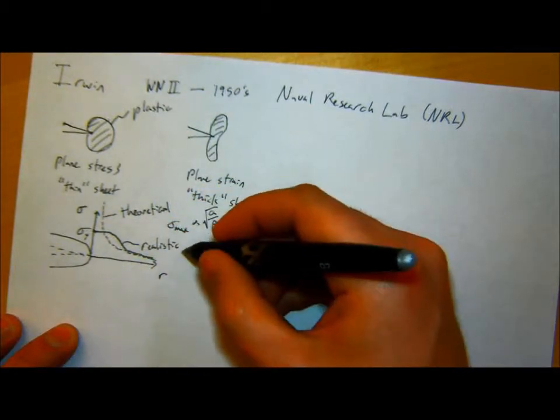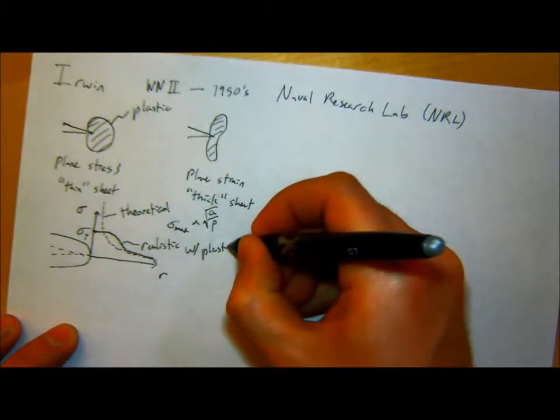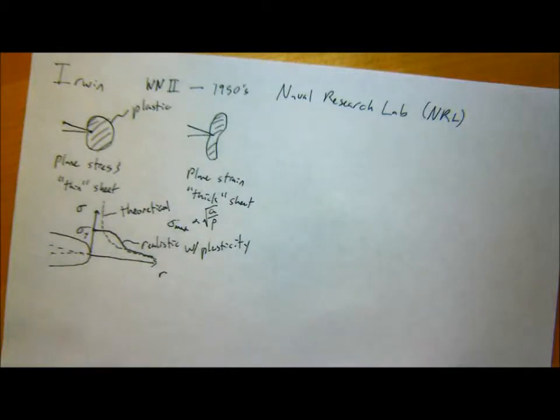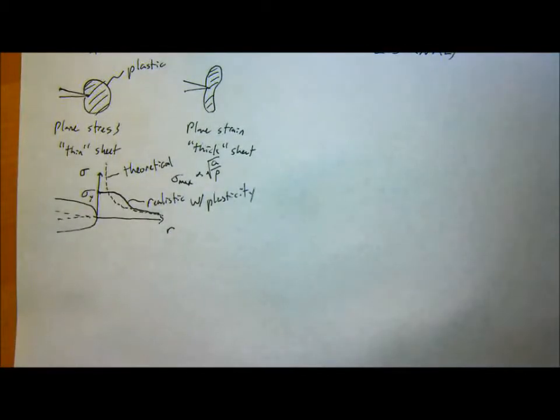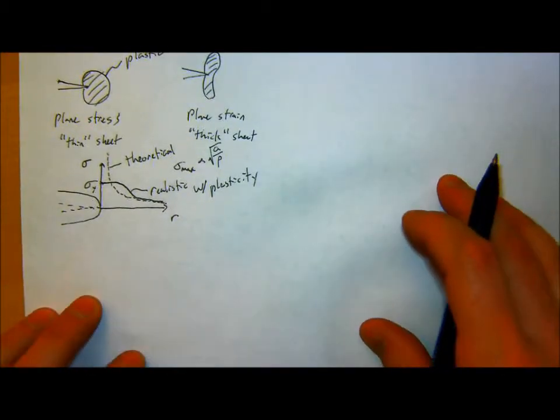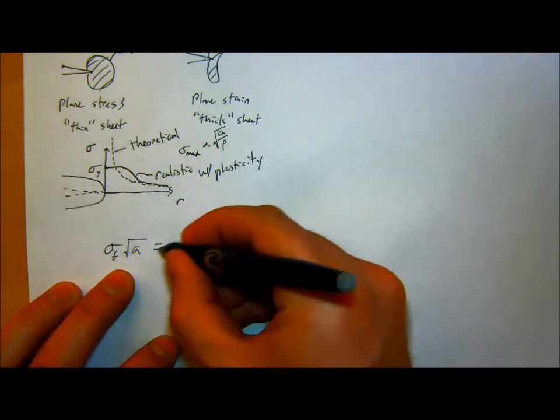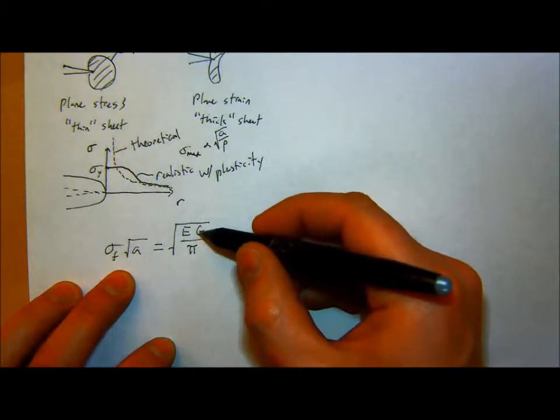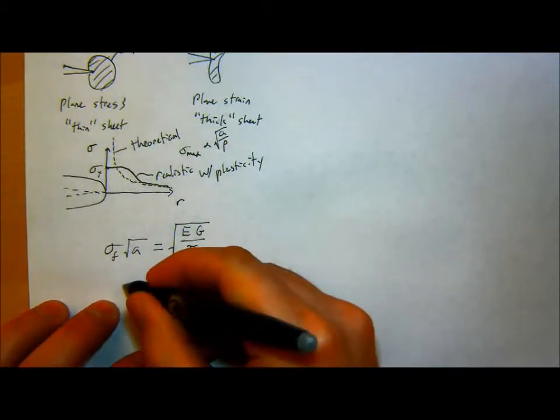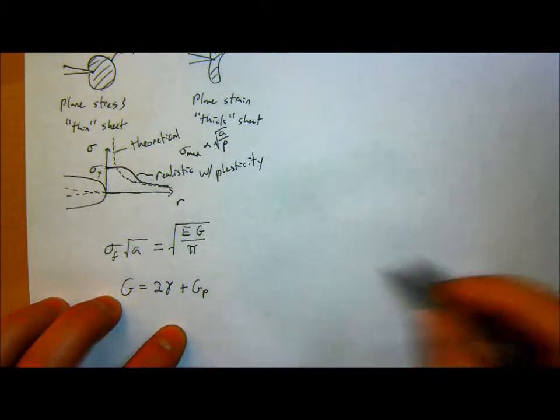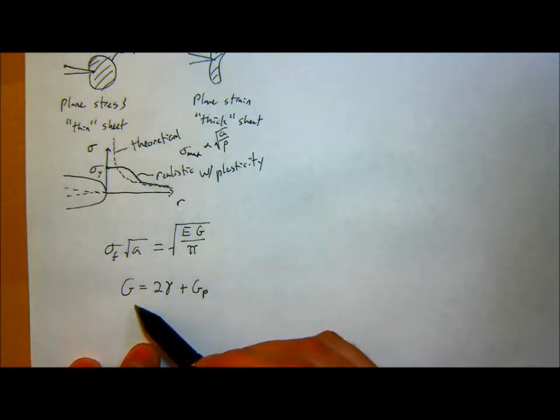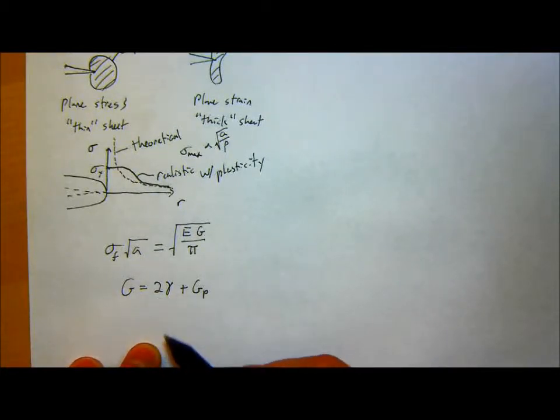So Irwin then proposed a slightly modified version of that fracture toughness relationship. So now we have sigma f square root of a instead is equal to the square root of EG over pi, where before I had a 2 gamma for the surface energy. This G now is going to be that surface energy term plus plastic dissipation energy. Friday, I'll go into more detail about exactly how we get this G, but really simply, there's some energy that's dissipated plastically as I deform this crack.